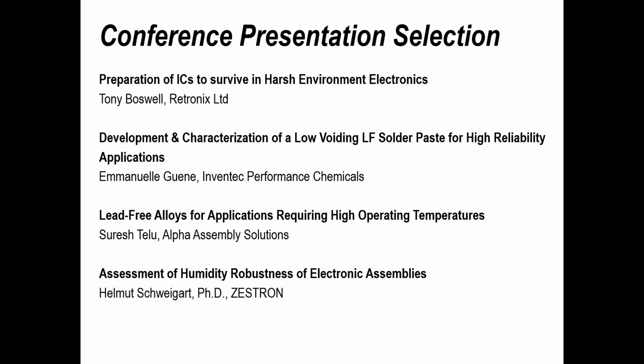then looking at improving on the performance of those materials, because when you look at temperature cycling of some of the tin, antimony and HMP solders, the performance in terms of the joints is not necessarily as robust. It will stand up to high temperatures, but temperature cycling can be a problem.